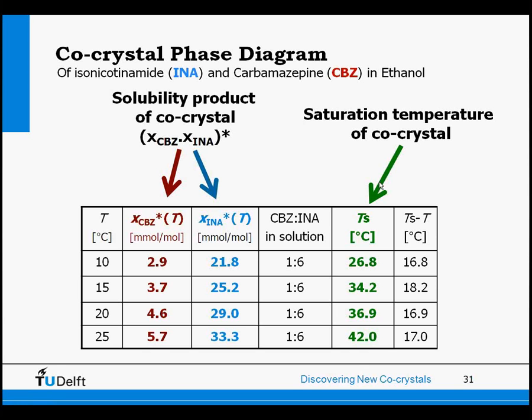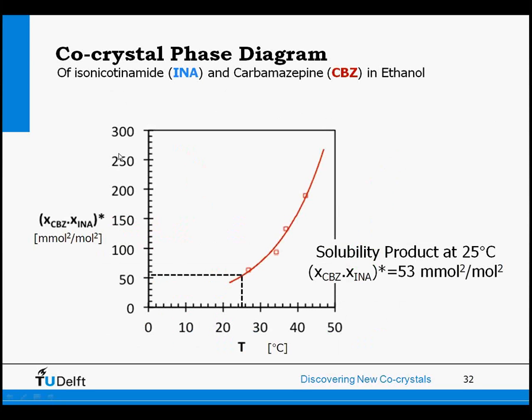So then we assume that the solubility of the co-crystal is determined by the solubility product. And we have measured our saturation temperature of the co-crystal of carbamazepine with isonicotinamide, and we know the concentrations we used. So we can determine the solubility product of the co-crystal, so the mole fraction of carbamazepine times the mole fraction of isonicotinamide, and we know the saturation temperature that belongs to that solubility product. That is the green number that is in this row. So we can plot that. So the solubility product as a function of temperature, and we get this red line.